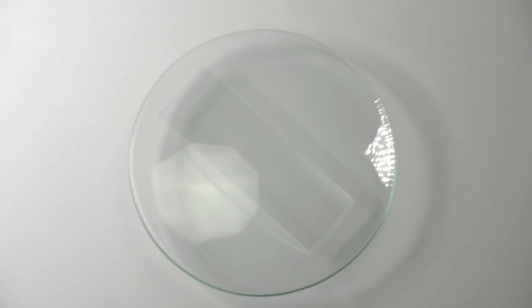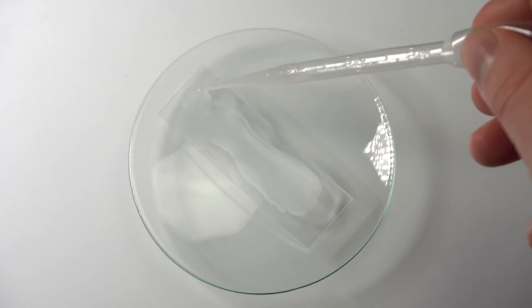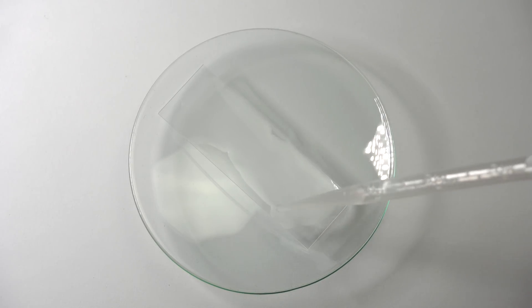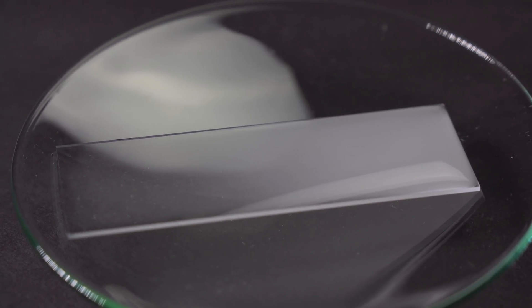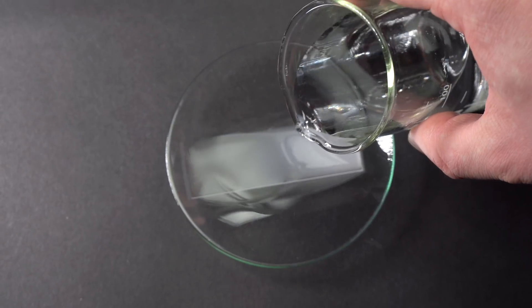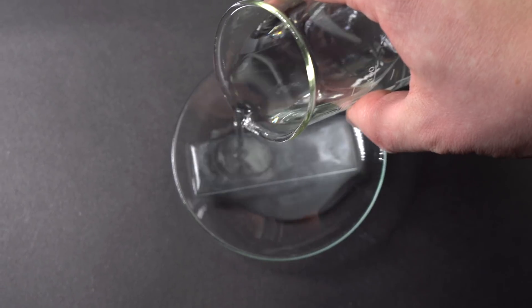I ran such an experiment during my second attempt. This time I took a purified microscope glass plate and poured some 2% tin chloride solution on the surface to activate it. After activating the surface, I poured 10 drops of glucose and 20 drops of silver ammonia on it.